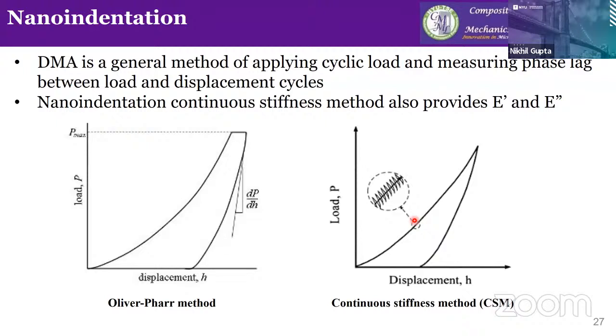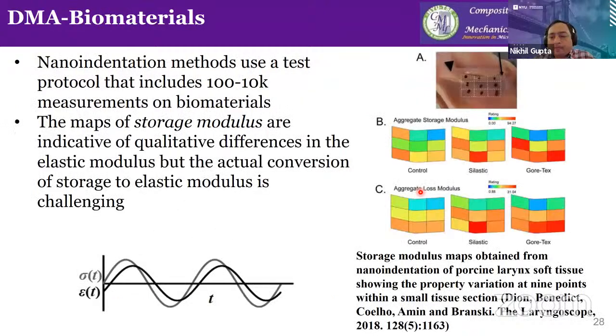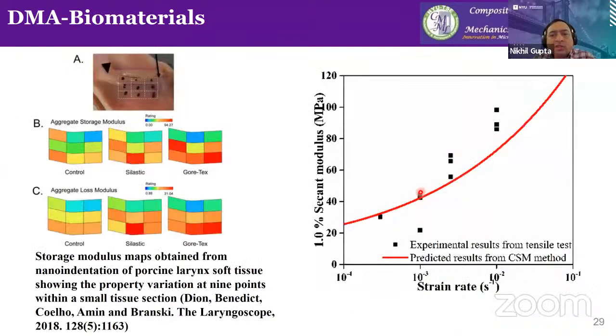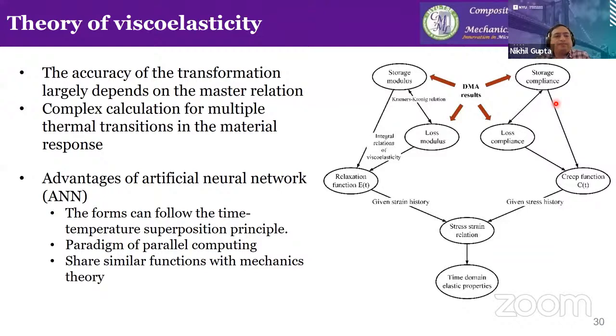From the Oliver-Pharr method, the more evolved method is the CSM method. It's called the continuous stiffness method, in which the load is constantly oscillated. And based on this frequency, you can measure the elastic modulus under different conditions. So the CSM data is what we are using here for conversion to elastic modulus. Once you are able to convert the storage modulus to elastic modulus, here you can see that the fitting on the data with our model is quite close compared to what has been measured from storage modulus here. So the method can be useful for a wide range of accuracies.